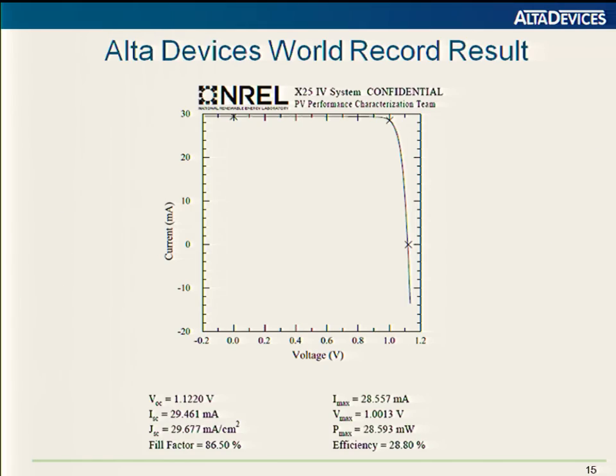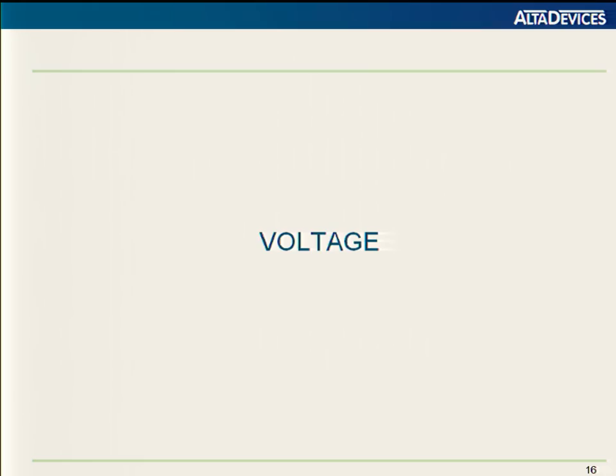With this, we're able to achieve 28.8% efficiency certified by NREL. This cell has a VOC of 1.122. We have achieved 1.126 in a different device. And I believe this is the first gallium arsenide device with operating voltage above 1 volt. The JSC and fill factor, on the other hand, are very comparable to other groups within the industry. So even thinning the absorber with the reflector, we're able to maintain the JSC.